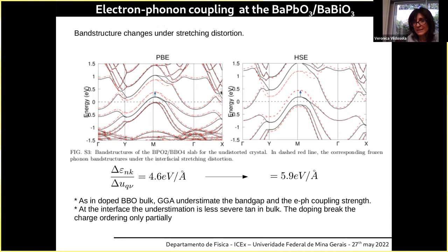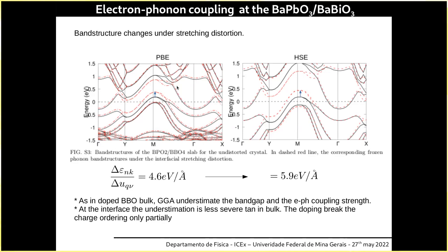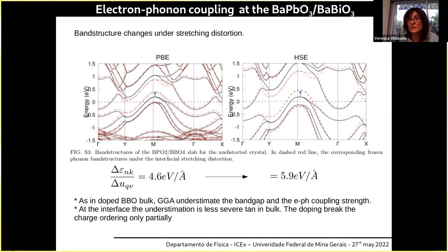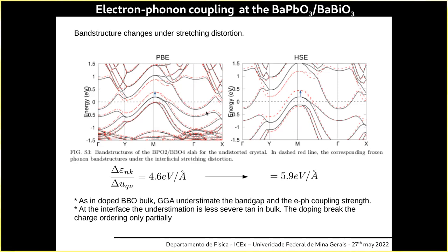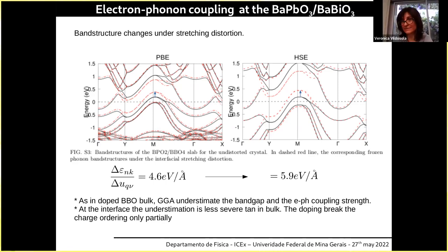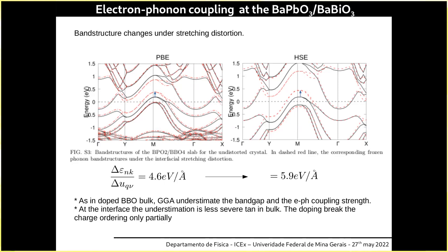The black line is the unperturbed system. When you induce the stretching distortion, you have this red line and it is shifted, but in the unperturbed situation, it is not an occupied band. This is the band coming from lead. Okay, quite interesting. What would be nice to do, and what we are trying with tin, is to induce a complete charge ordering breaking, because that would be similar to the superconductor cases. Exactly. Okay, thank you very much.